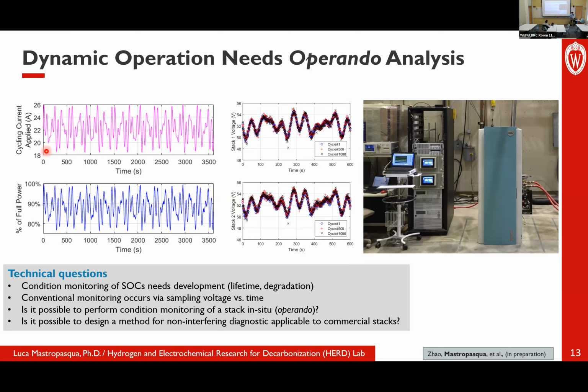For 3,500 seconds, that was the profile, and then we repeated that cycle for 3,000 hours. The figures on the right report the different cycles in terms of stack power and voltage. So basically, we operated the SOEC for a long time using extremely variable, fluctuating profiles of input current, and then measured the voltage to see if that was degrading as a function of time.